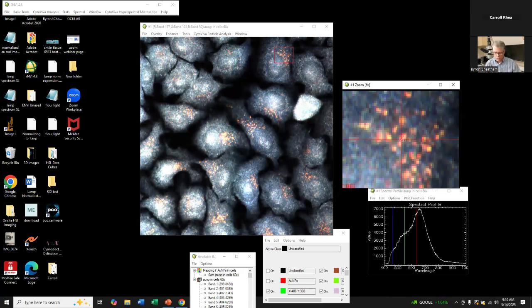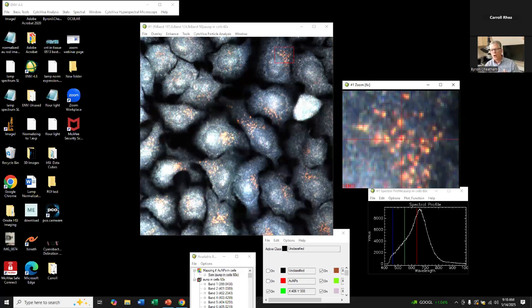Now, these gold things that we see in the tissue are, in fact, gold nanoparticles that have been internalized by the tissue. And we know they're in the tissue based on the spectrum that we see, where we see a pretty broad full width half max compared to if we were just looking at this nanoparticle in solution. But also, if we were to focus up and down in the spatial Z-axis with the microscope, you would see nanoparticles appear and disappear in different focal planes of these cells. We're on a specific focal plane where the nanoparticles appear the brightest in this image. That's why they're so visible.